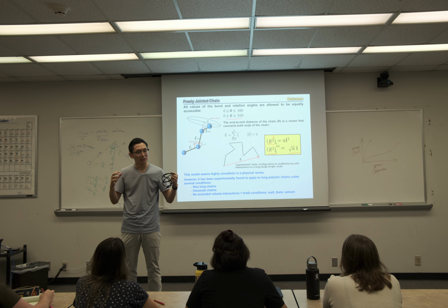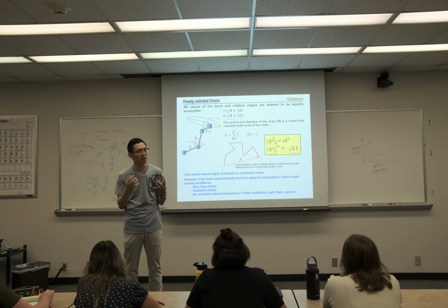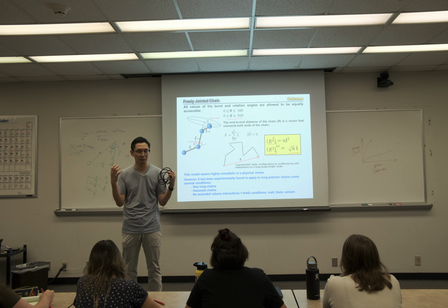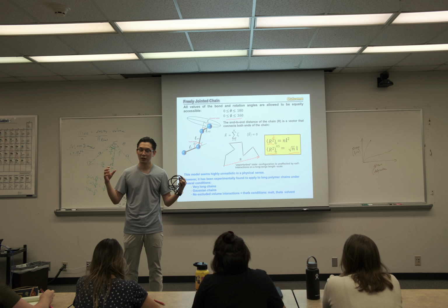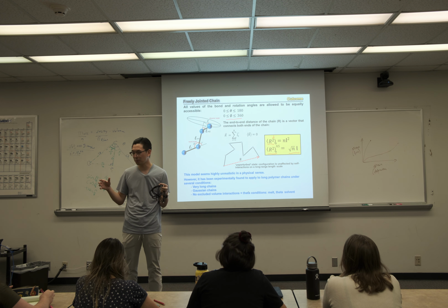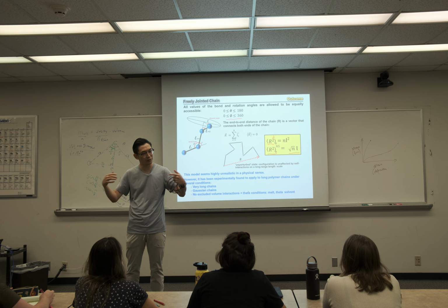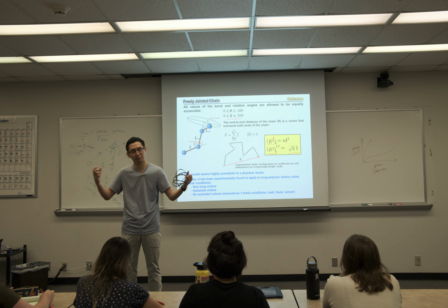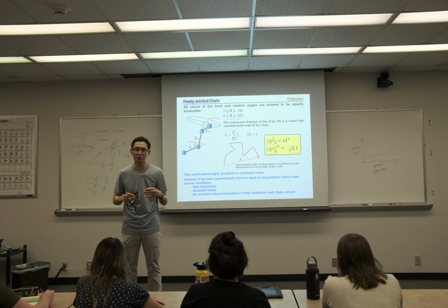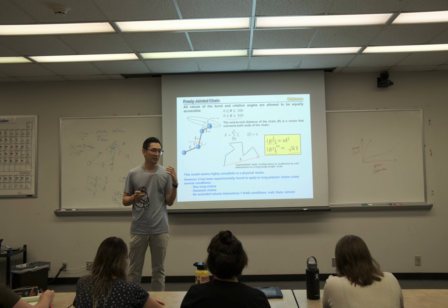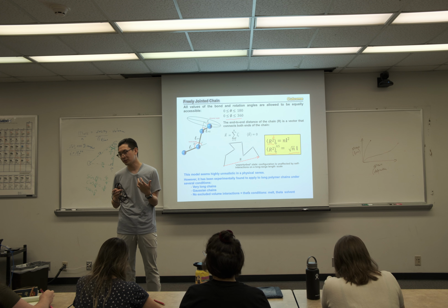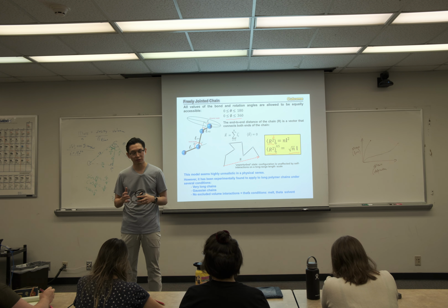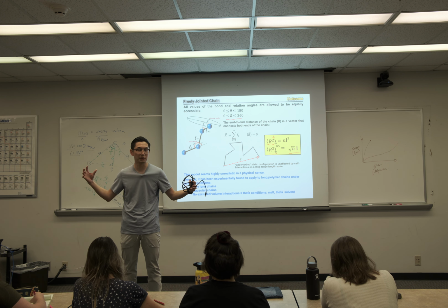The expansion basically comes from the excluded volume, they want to expand. But if another neighbor is occupying the same space, the forces cancel each other out. So this is the very special case in melt states, because the chain can't see if it's surrounded by itself or its neighbor, so the forces cancel each other out.